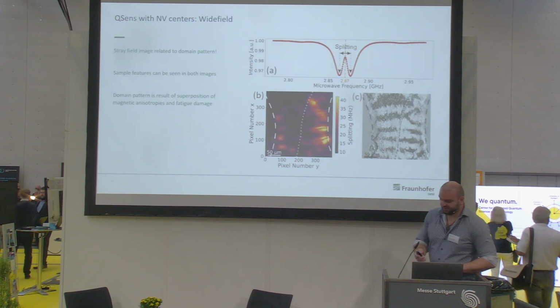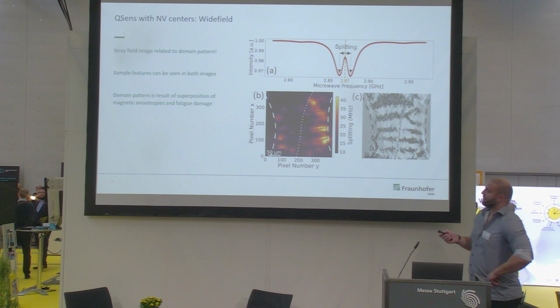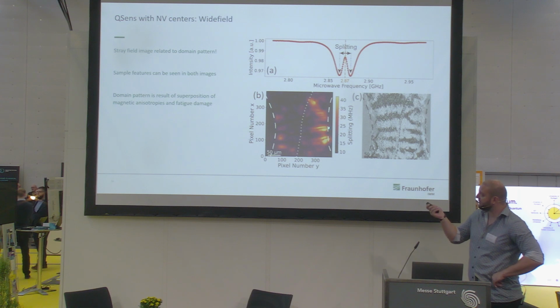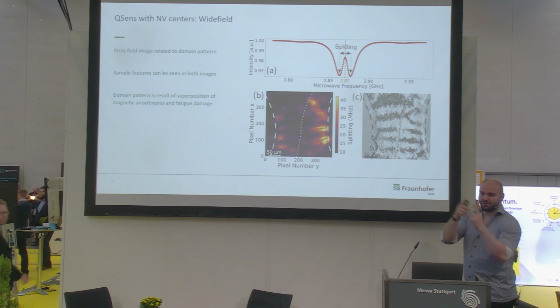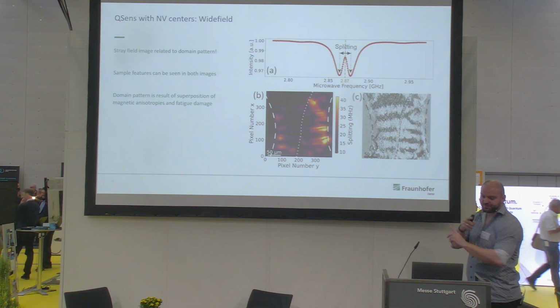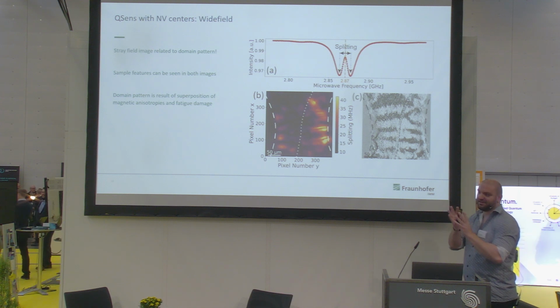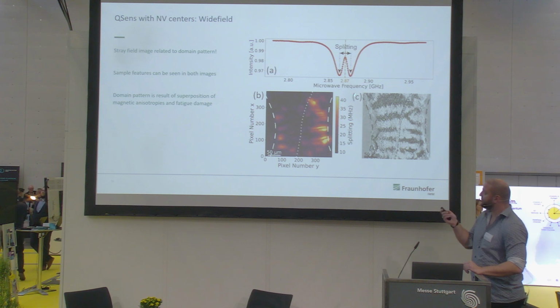So what we can see from this is an ODMR spectrum, and the splitting is, of course, here between these two dips. We didn't calculate the absolute magnetic field in this case because this is an average of all NV directions in the diamond, which gives us more or less an average value only. So we left it here with splitting, in case you're just wondering why there's no magnetic field.